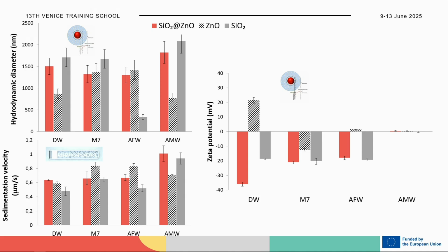What we observe from this characterization is that, based on increasing the ionic strength of our media, we observe a kind of destabilization. So we observed a higher hydrodynamic diameter, a higher sedimentation velocity of the particles, and the zeta potential that went close to zero if we move to the artificial marine water.